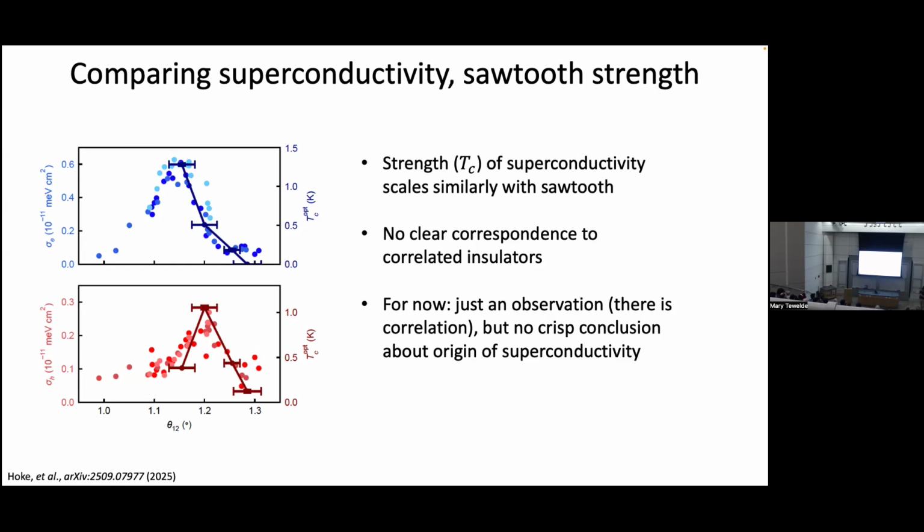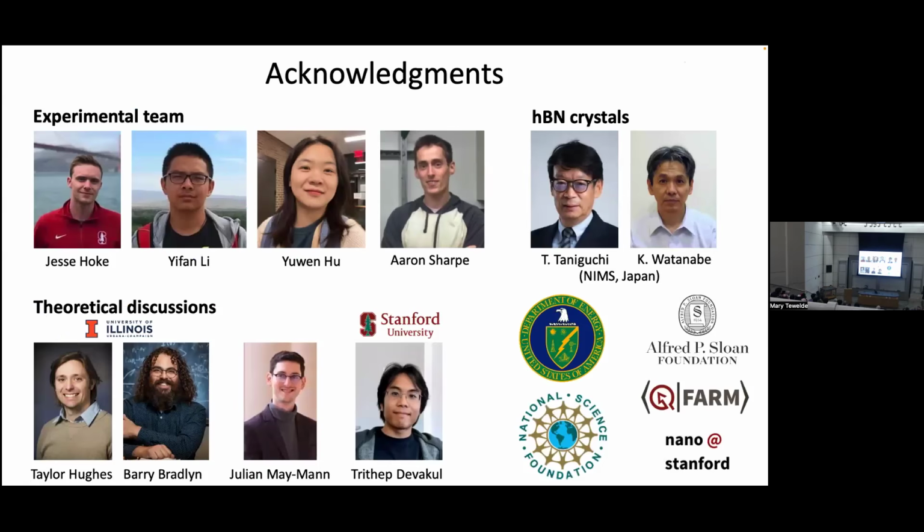We measured it locally as best as we could with thermodynamic, with the SET, and then we took it out, measured it in the same device. The twist angles, by the way, didn't change as a result of all the fab that we did, and we can now compare it to the superconductivity as well. This is still in progress, still to be figured out: how much can you interpret from that measurement? But anyway, I think it's a nice example of combining global and local approaches.